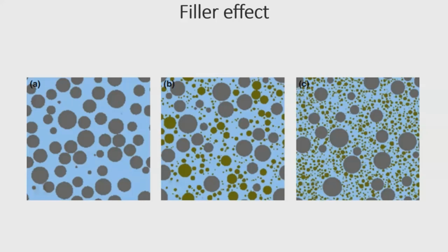Filler effect is characterized by being inert and non-reactive on its own. However, it favors the development of a more densified microstructure. This happens through two mechanisms. The first, the filling of interstitial spaces between cement grains, as we can see in the pictures, promoting densification. And secondly, an increase in the surface area available for the nucleation of hydration products such as